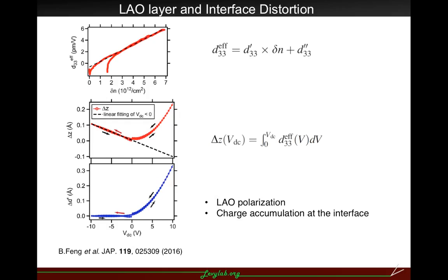The effective piezo response strain tensor element d33 has a linear relationship with the change of the carrier density, and the surface displacement can be calculated by integrating this strain tensor with respect to the DC voltage applied to the interface. And there is a difference between both sides of the metal-insulator transition point. When the sample is in an insulating region, the surface displacement is linear with the DC voltage, and when the sample is in a conducting state, the displacement is related to the charge accumulation. And this linear part is due to the LAO polarization, so the interface distortion can be calculated by subtracting the LAO polarization part.